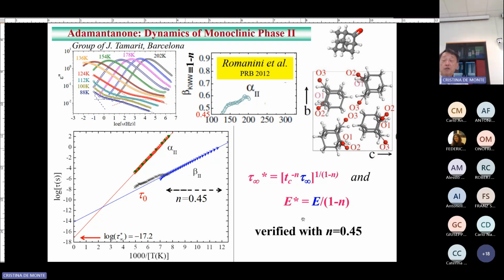They are translationally ordered, but orientationally they are disordered. There's a dipole moment here, and you can probe that by dielectric, which was done by the group of Tamarit. I think Simone is a co-author of this paper too. And then you see dielectrically the alpha and the beta, the so-called JG relaxation here. And you know the coupling parameter in the coupling model equation. This one here, you see the 1 minus n, that is the Kohlrausch exponent, as I mentioned already, which is also part of the coupling model.